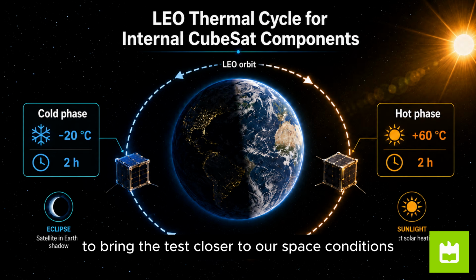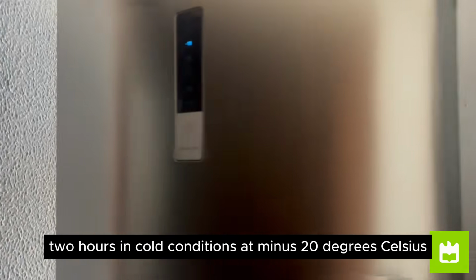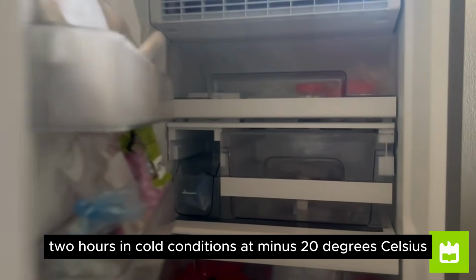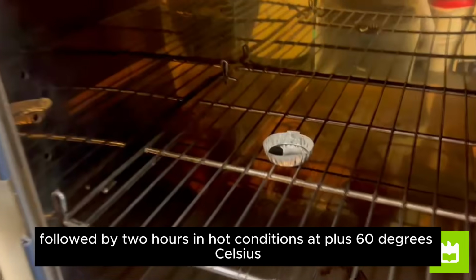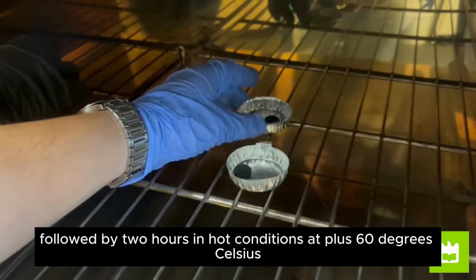To bring the test closer to space conditions, the samples are also exposed to thermal cycling: 2 hours in cold conditions at minus 20 degrees Celsius, followed by 2 hours in hot conditions at plus 60 degrees Celsius.